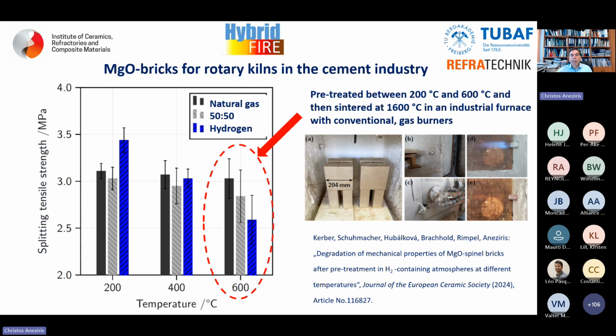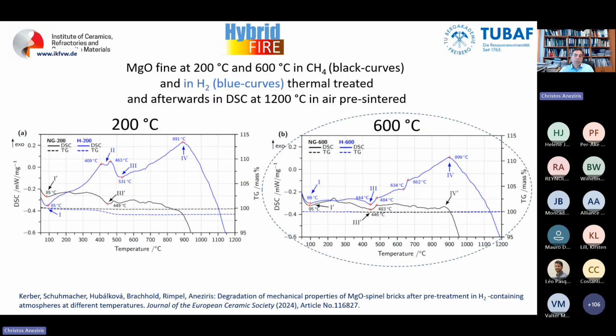And this is detrimental if we keep in mind that such kind of bricks have to live more than 1 year in the rotary kiln. Somebody would say, do you see this only in case of strength? No. You can see within a kind of calorimetry, you can identify different kind of reactions. On the left, the blue curve is a pre-treatment at 200, on the right at 600. And the black curve is the kind that we have normally in natural gas. So we see, in spite of the fact that we speak about hydrogen, at different temperatures, different kind of reactions will appear.